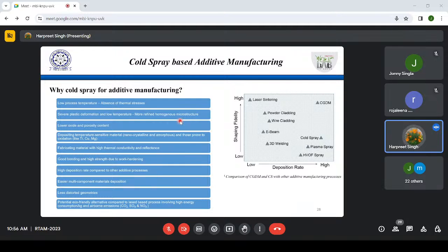So if you see the fatigue strength of cold spray processed parts, it is very good actually. Why? Because we are getting net compressive stress in the deposits, whereas in other processes you will get net residual stress. Residual stress will be tensile in most of these processes. But here it will be compressive because you have severe plastic deformation, which gives net compressive residual stress, which is helpful. Low oxide content and porosity content, of course, we understood.